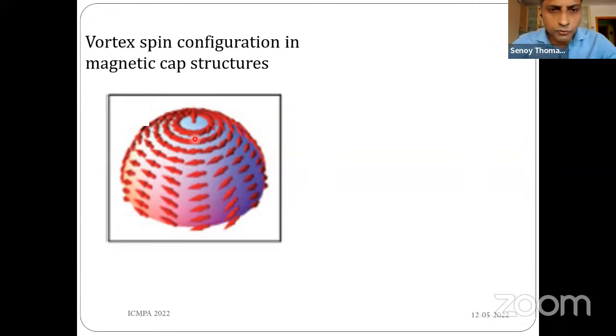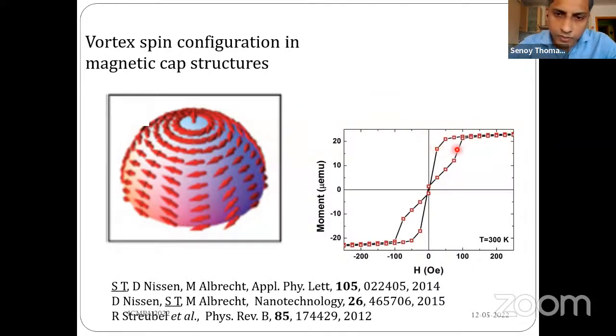Now if you measure magnetization as a function of field curve for an assembly of such soft magnetic nanocaps, you could end up with a loop similar to the one which I have shown here. Basically, if you decrease the field from a positive saturation, at some intermediate external magnetic field there is a drastic reduction in magnetization, and we end up with negligible remanence.